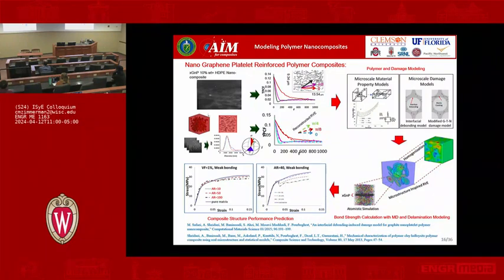You wouldn't know that until you do some simulation, atomistic simulation called molecular dynamics. We do that, and we actually put these graphene platelets in there, and we pull them out and see what the strength is in order to pull that out. Then we put that information into this type of model that has the platelets, has the matrix, but also has the strength of the bond between them. Now we have a complete model. We have a twin version of this actual process, statistically the same, and also otherwise the same.